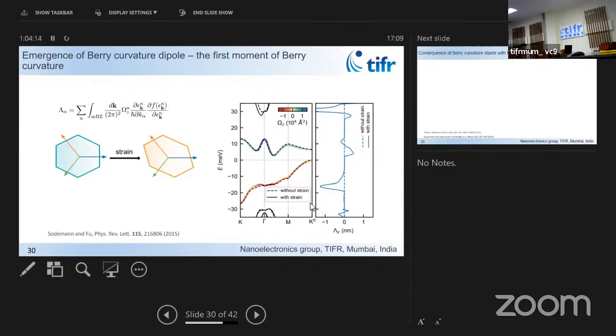And now, if you plot the Berry curvature dipole, this plot shows the distribution of the Berry curvature in k-space. This is energy. You have negative, positive, and this is the quantity which is called the Berry curvature dipole. Now, the dotted line is when everything is symmetric, which is this blue lattice. It's exactly honeycomb. The Berry curvature dipole is identically zero. But if you now measure the Berry curvature dipole in the strained lattice, it's not zero. In fact, at certain points where the Berry curvature is large, the Berry curvature dipole, which is the first moment, becomes quite large. Okay, and that's what we focus on.